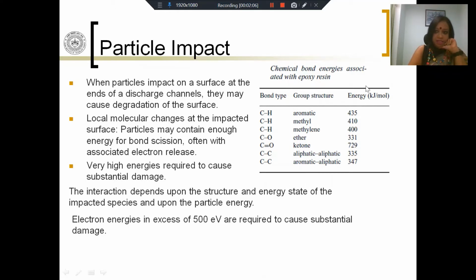For example, if you look at this table, which gives us the chemical bond energies associated with epoxy resin, there are various kinds of bonds in a polymer. You have CH bonds, the aromatic CH bond, the methyl CH bond, the methylene CH bond, CO, COO, CC. Each of these bonds has associated with it a certain energy that is required for the bond to be broken. For example, the aromatic CH bond needs something like 435 kilojoules per mole. For the ketone bond, we need 729 kilojoules per mole. So we actually need this amount of energy for bond scission to occur. Electron energies in excess of 500 eV are required to cause substantial damage.